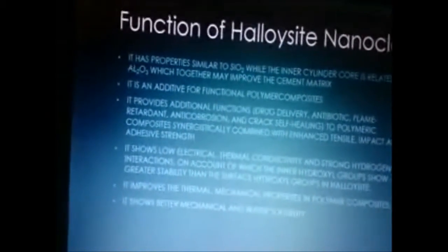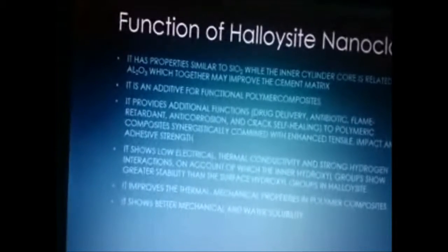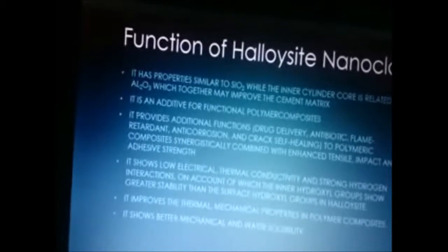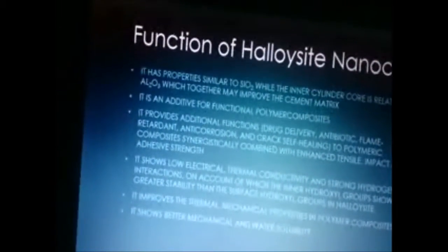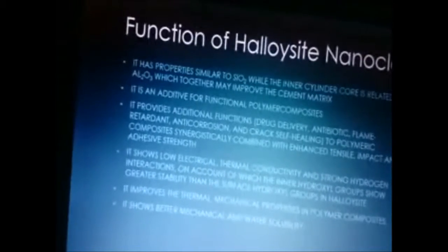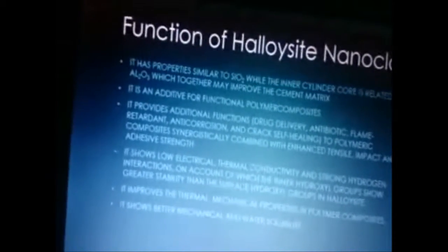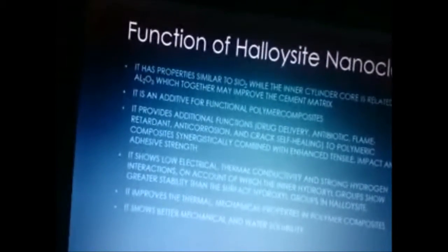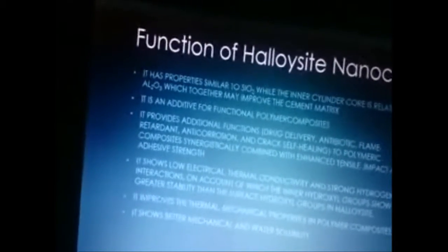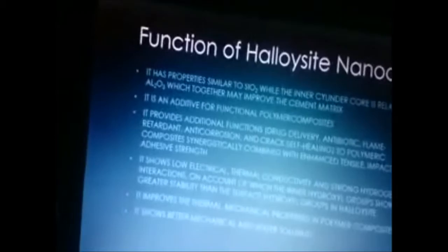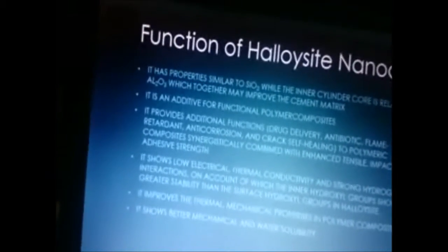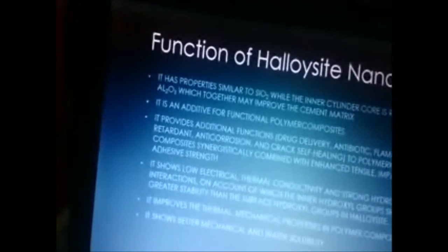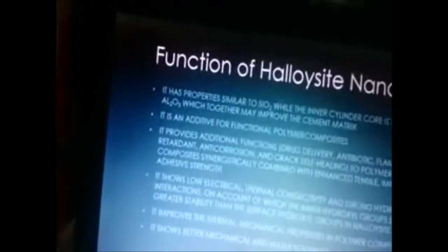Doping loaded clay nanotubes into a polymeric matrix provides a kind of ceramic skeleton, and these skeleton bones are loaded with functional chemicals like real bones loaded with marrow. Tunable controlled release of active agents through synthesis of artificial nanocaps at the tube endings, and Halloysite lumen enlargement by selective etching, allows for tubular nanocontainers with chemical release times from 10 to 200 hours and a loading capacity of calcium up to 30%.